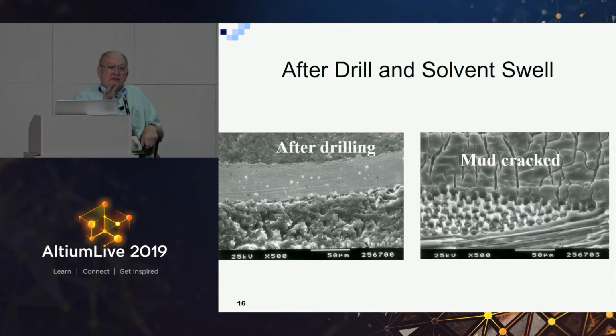Now, none of this exists in the drilled hole arena, because the drilled hole is so much bigger. But when you get really, really tiny with the laser-drilled one, this stuff all starts to pop to the surface. I don't want to frighten you away. I just want to sensitize you to your purchasing: purchasing an HDI board needs more engineering attention than purchasing conventional multilayers. Be sensitive to the fact that it's a tougher technology and it can be done wrong. And you don't want to be the recipient when it's done wrong, because it's your product, your board, that's being done that way.